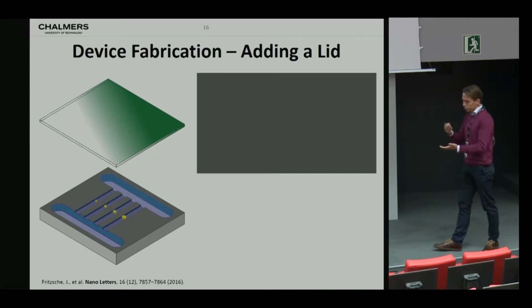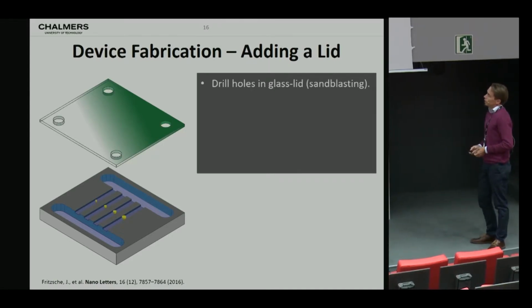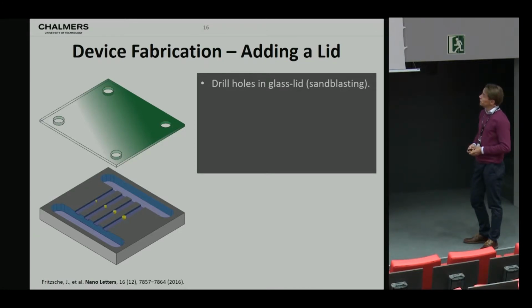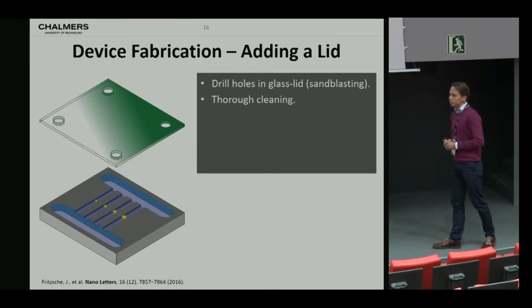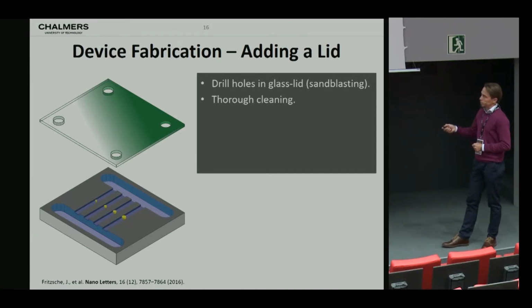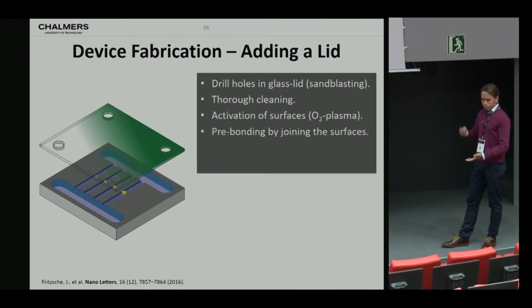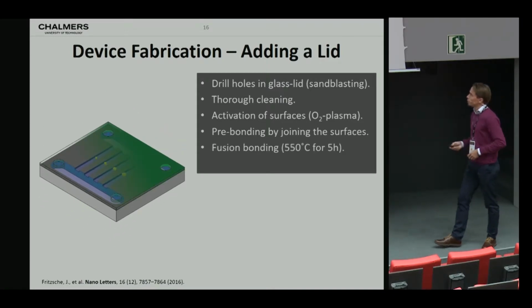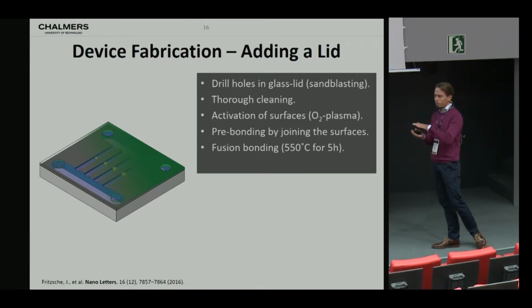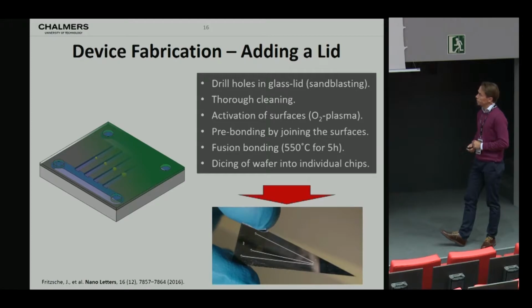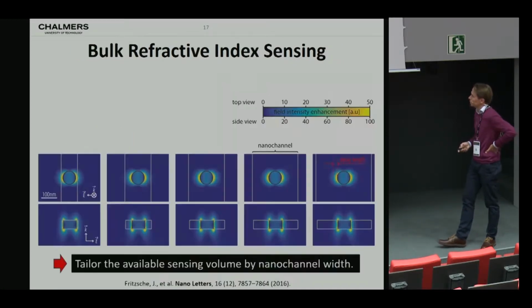In the last step, it's time to seal the whole thing. So we have a borosilicate glass lid into which we have to drill some holes in order to access the microfluidic system. We do this by sandblasting. After that, we have to very, very thoroughly clean this because any dirt will basically destroy the seal here. We activate the two surfaces by means of oxygen plasma, pre-bond them by simply joining them, and then apply fusion bonding at 550 centigrade for 5 hours to create a tight seal, and eventually dice the wafer into individual chips, which could look like this. What you see here with the naked eye is the microfluidic system, and the nanofluidics would be located down here.